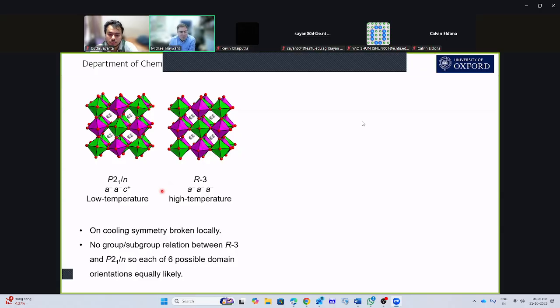Or another way of thinking about it is that having 3 tilts that are out of phase along X, Y, and Z, we have no indication as to which direction we should put in phase. Should it be X or Y or Z? That gives me 3 choices. And then the in-phase tilt can either be clockwise or anti-clockwise. So my total number of choices is 6. So I can basically have 6 orientations of this tilt pattern relative to this one. And they're all equally likely.